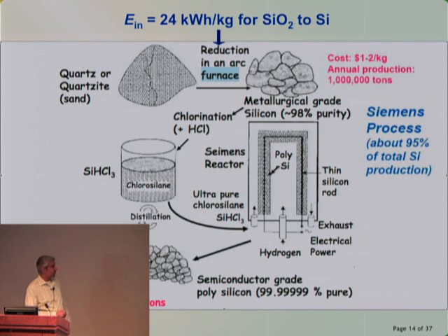But that's not even where we want to begin, because that gives us about a price point of $1 or $2 per kilogram, but that's metallurgical grade silicon, and we can't make solar cells out of metallurgical grade silicon yet. People are working on different ways of isolating impurities, but I'm just talking about the traditional industry, what you could buy more or less off the shelf today. So then you go through this complicated Siemens process, which, to get to the purity levels you want, goes up to $25 a kilogram. So about an order of magnitude change from metallurgical grade to this pure grade.